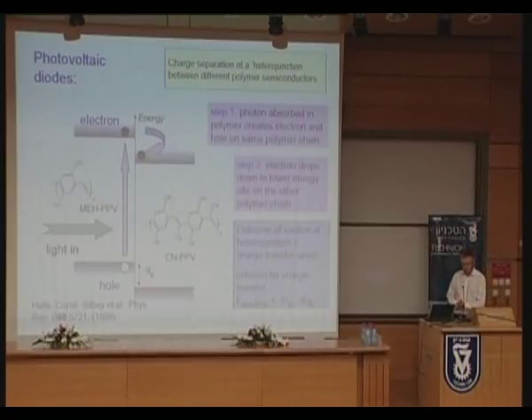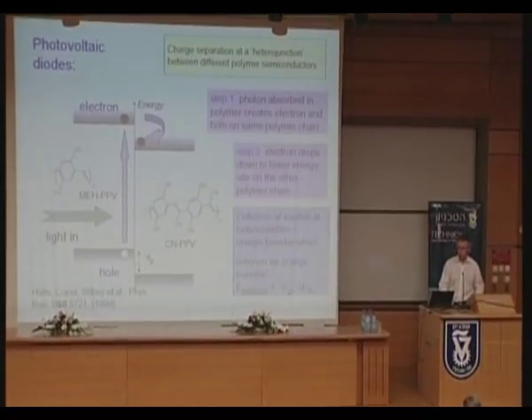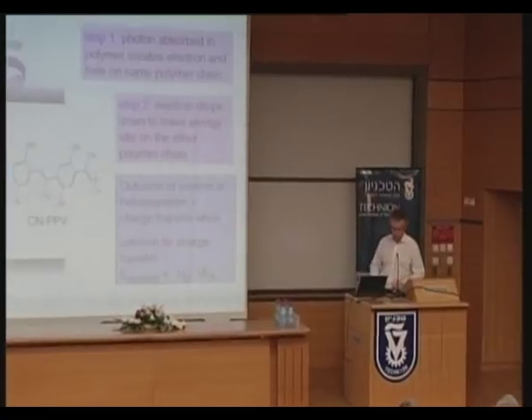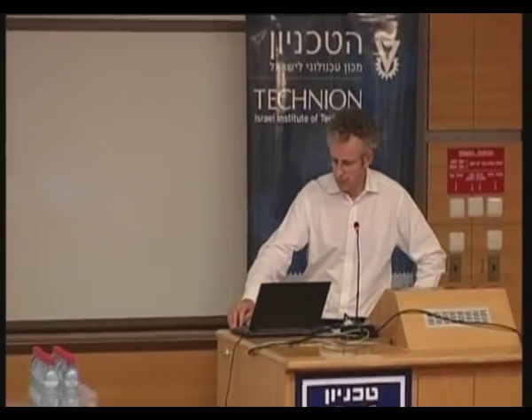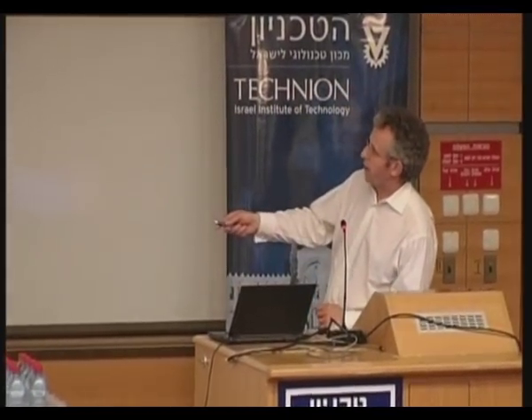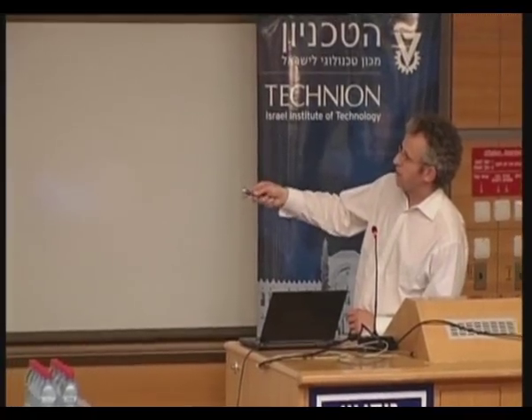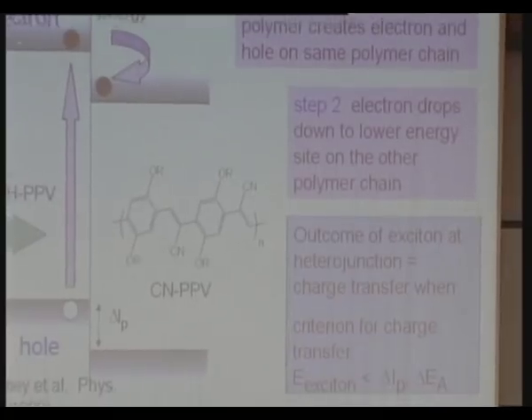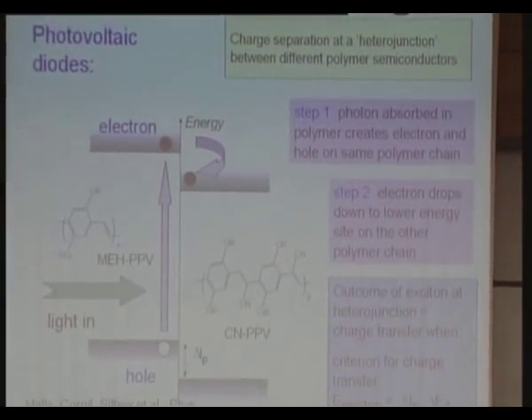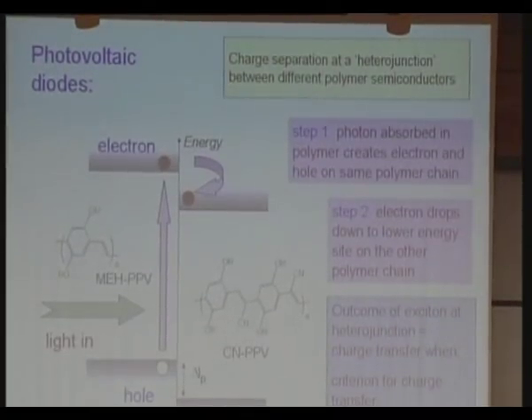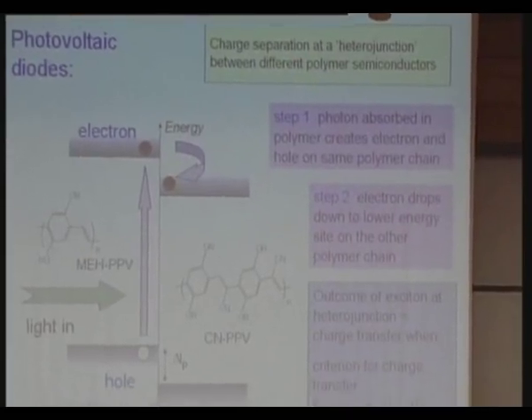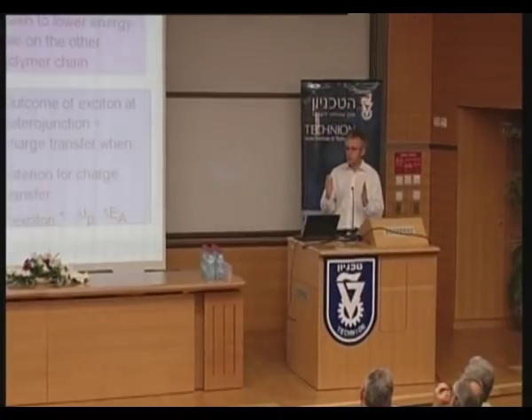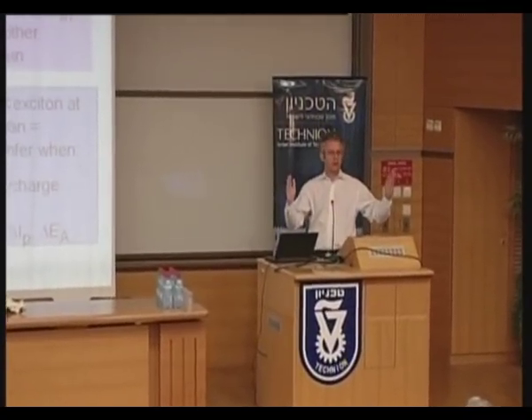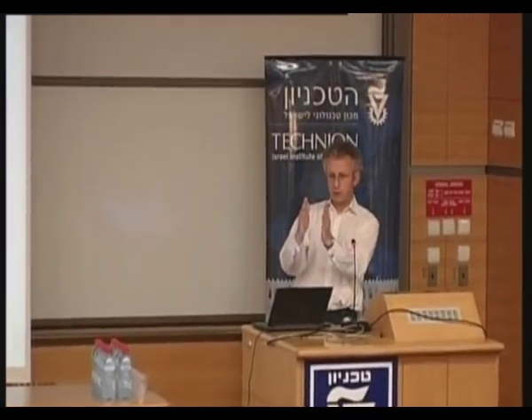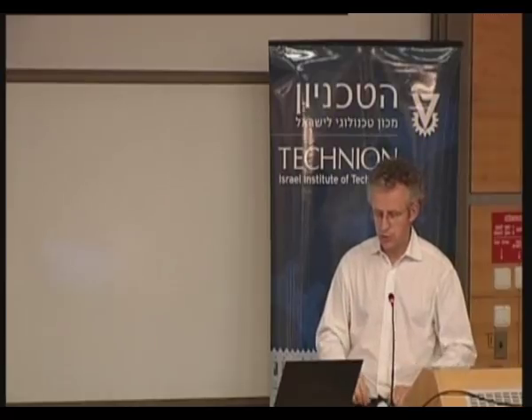Well, that doesn't instantly give us an efficient photovoltaic diode. And I should say that there's a huge level of interest at the moment in finding ways of using this sort of structure to make cheap, large area solar cells. The problem is that in order for it to work, every photon absorbed in the bulk semiconductor has got to create an excitation which bumps into some heterojunction in order to charge separate before it gives up the ghost and emits a photon. And the problem is that it is a rather short distance that it'll travel, typically 10 nanometers. So you need perhaps 200 nanometers of thickness to absorb light, but if only the light that is absorbed within 10 nanometers of an abrupt heterojunction between one material and the next is going to be useful, then it will produce a low efficiency device.